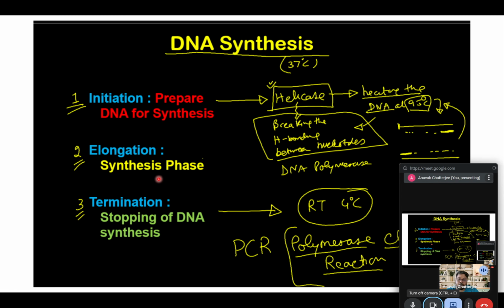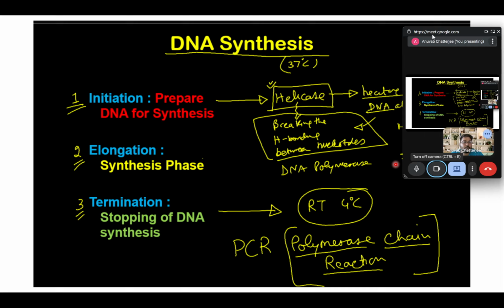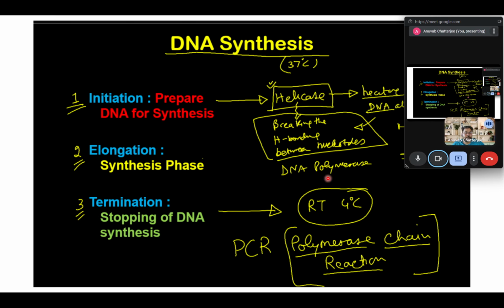In the synthesis phase, we would require a polymerase that can do it. There were various different polymerases that could have been used, but the major breakthrough came with the discovery of Taq polymerase, or Thermus aquaticus polymerase, that can work at a very high temperature, around 72 degrees Celsius. So the optimum temperature for synthesis of Taq polymerase is 72 degrees Celsius, not the normal 37 that we would expect. And also it is heat resistant. So you can heat the entire polymerase up to a very high temperature and still it would not denature.